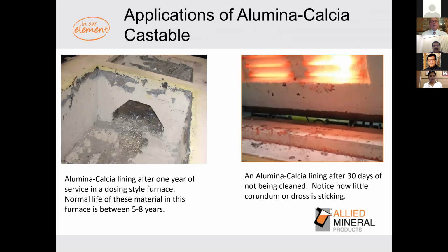Michael alluded to the dosing furnaces that were feeding his machines through the dies. And here's a dosing furnace using the calcium-based materials. These things are lasting 5 to 8 years, with, again, almost zero penetration and very easy peelability. Same thing with a heated launder. Again, after 30 days, and historically, workers are terrible about cleaning the walls off of the aluminum, and this is easy to clean because it doesn't stick.